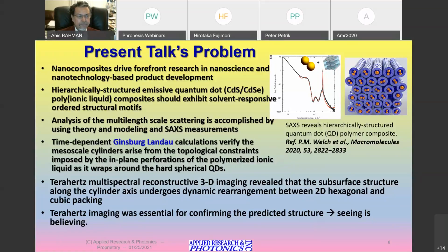artist rendering. So we have conducted Terahertz multispectral reconstructive 3D imaging, by which it was revealed that the subsurface structure along the cylindrical axis undergoes dynamic rearrangement between 2D hexagonal and cubic packing. And Terahertz imaging was essential because everything else can see only the surface, not under the surface in 3 dimensions without being in a destructive mode.